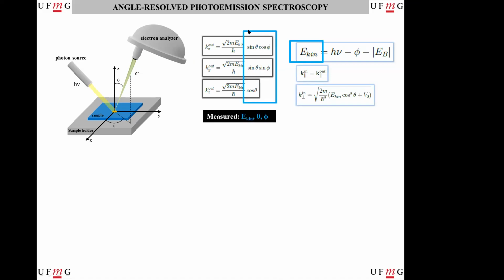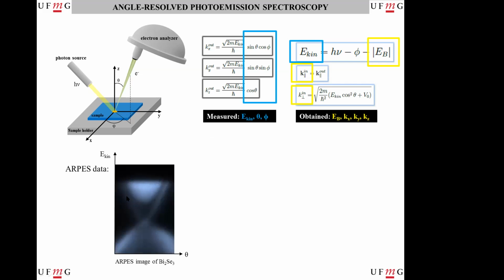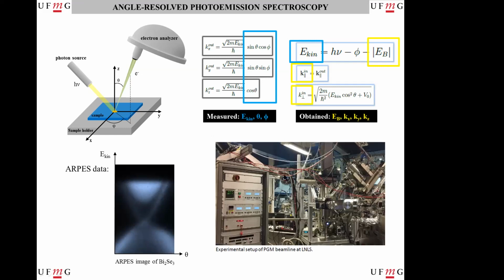So what we measure is the kinetic energy of the electrons and the angles at which the electrons go inside the electron analyzer. And from these measurements, we can obtain the energy of the electrons inside the solid, which is called the binding energy, and the momentum of the electrons inside the solid. Here is an example of ARPES data, as I showed before, the Dirac cone of bismuth selenide. And here's a picture of the experimental setup of the PGM line at the Brazilian synchrotron located in Campinas.